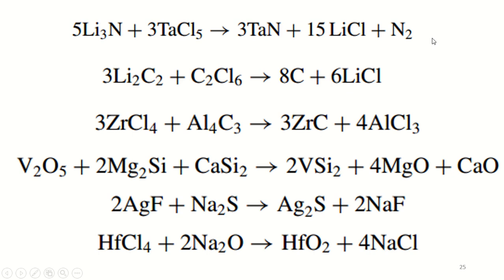The covalent TaCl5 and highly reactive Li3N form the desired product TaN together with lithium chloride, and lithium chloride may be dissolved readily to leave pure TaN.